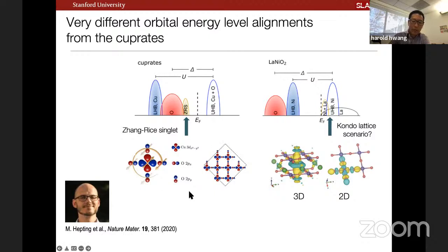And so let me just give you a cartoon summary of the cuprate landscape first. So in the cuprate problem, right, we're starting from this notion of a charge transfer insulator. And so you have a lower and upper Hubbard band, primarily of d x squared minus y squared origin. And then you have kind of this band of oxygen, if you want to use this language, such that when you hole dope the system, what's rather interesting is you're actually kind of having something with holes of oxygen character coming out of the ligand field, right? So this notion of a Zhang-Rice singlet from the early days of cuprates gives you a nice understanding of both the nature of the doped hole, but the coupling to, say, magnetic fluctuations and so forth that's so relevant for that problem.